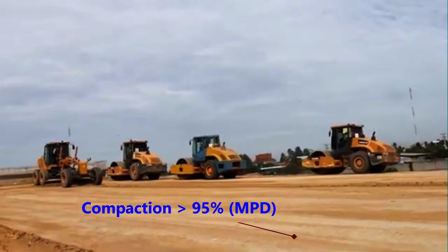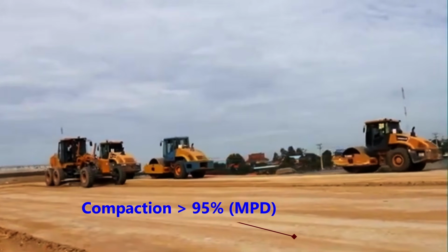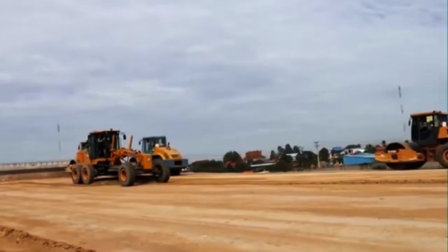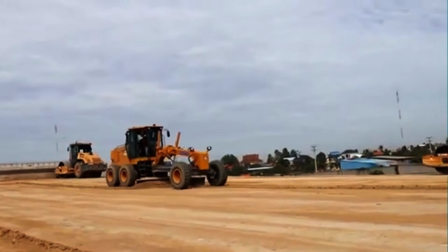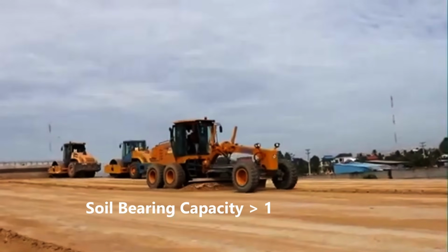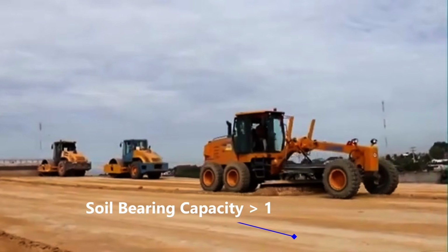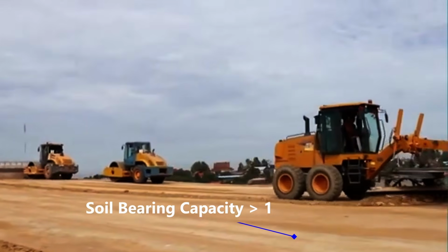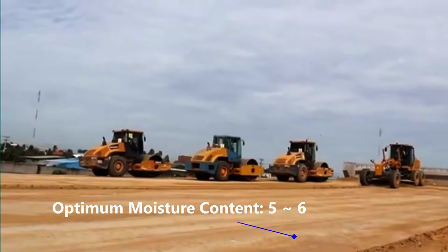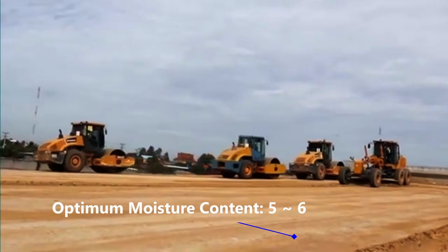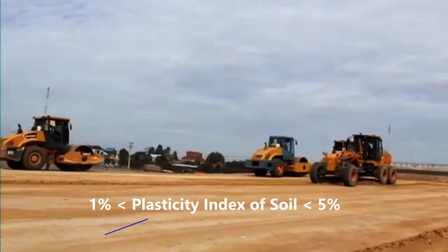For highways, modified Proctor density is used to determine the relative density. The specifications to be followed are as follows. The selected soil shall have a minimum soil bearing capacity of 1 and above. The optimum moisture content shall generally be within 5 to 6%. The plasticity index of the soil shall be between 1 to 5%.